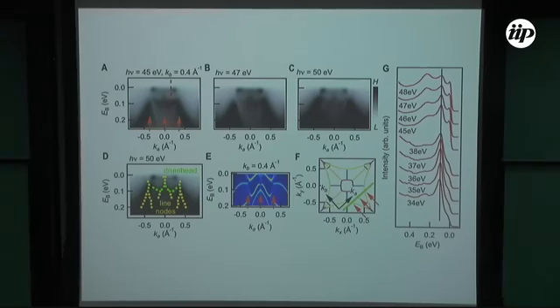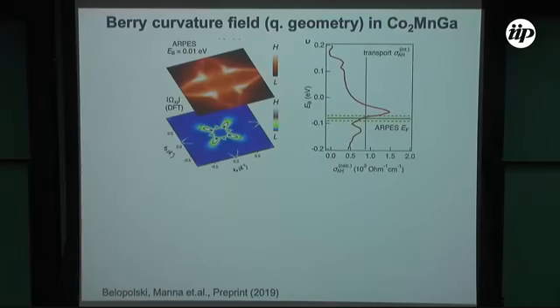So in other words, these line nodes are connected by these surface states that are drumhead-like. It's not completely flat, but there is about 100 millivolt bandwidth, which is really good, given that it's not a strongly correlated material. Okay, so now, all of that is ARPES, mapping out the Weyl node and all that. And all these Weyl nodes will contribute to transport. So now we are trying to see: what we measure in spectroscopy, is that a crazy thing, or is there a connection to transport?